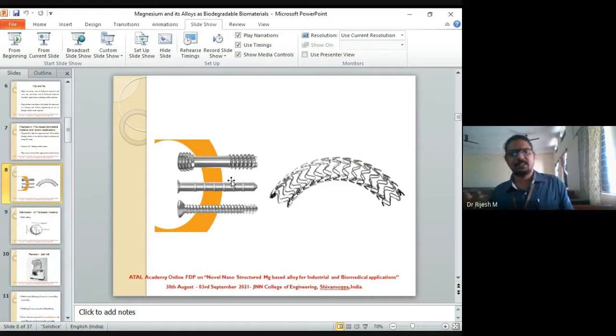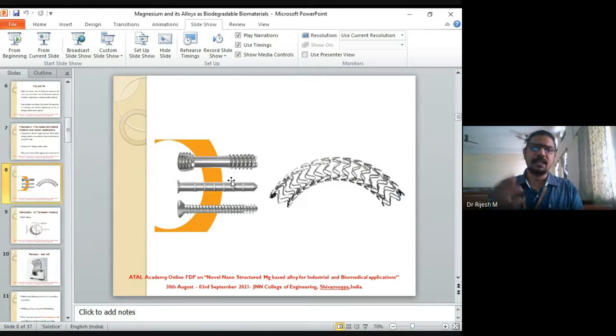Now we will see how we manufacture them. The typical method of manufacturing magnesium is casting and rod products. Now we have seen that when you go for casting and rod products, you have a lot of second phase particles. The second phase particles do very badly when it comes to corrosion because of two-phase galvanic corrosion and other issues. So even though magnesium and its alloys are normally processed by extrusion, casting, etc., the amount of wrought products used in dentistry and biomedical applications is considerably less. We generally go for a method called powder metallurgy.